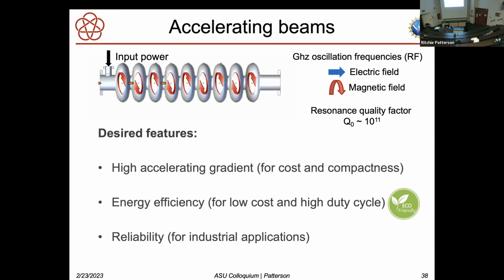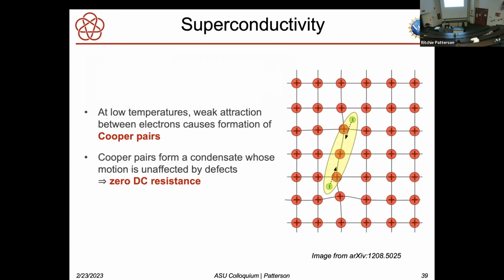What do you want in them? You want high accelerating gradient, so that you accelerate the beam quickly. You want energy efficiency for obvious reasons, and reliability. And I apologize here to the condensed matter physicists. Here's the nutshell of superconductivity. We know that at low temperatures, you get weak attraction between electrons to form Cooper pairs. And then those Cooper pairs form a condensate in the material that doesn't see defects. And as a result, there's zero DC resistance.